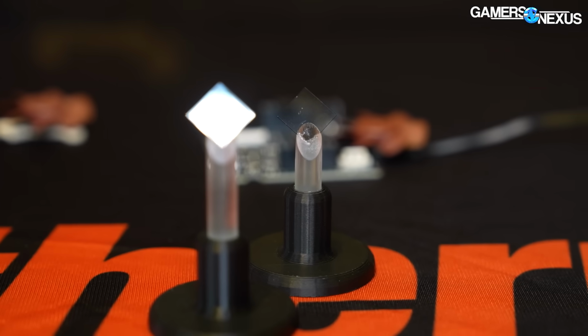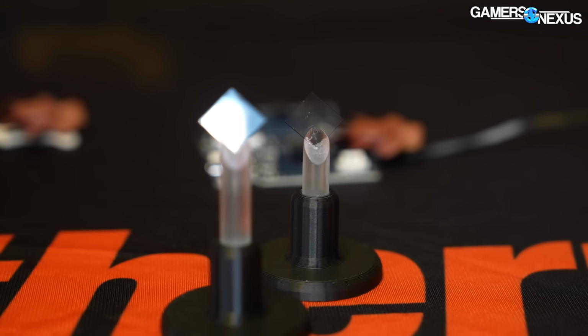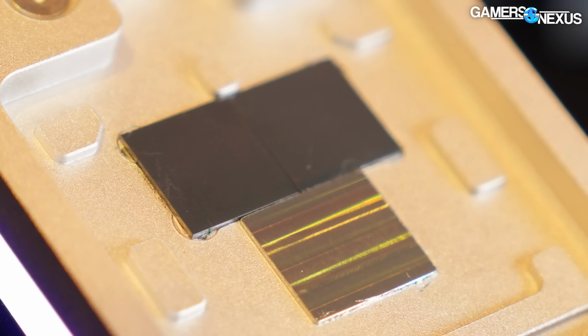But that's also a theory I read a lot of times on the internet: what if we use diamond? Because it has very high conductivity. This is a so-called CVD diamond, chemical vapor deposition. Basically a lab-grown diamond that's grown on a seed crystal out of a chemical vapor. So that's how it's grown, not under pressure like a natural diamond, but it's physically the same. It's just carbon in a perfect structure, so it has very high conductivity, about 2,200 watts per meter Kelvin, which is 5 times as much as copper. The copper is like 400, I guess.